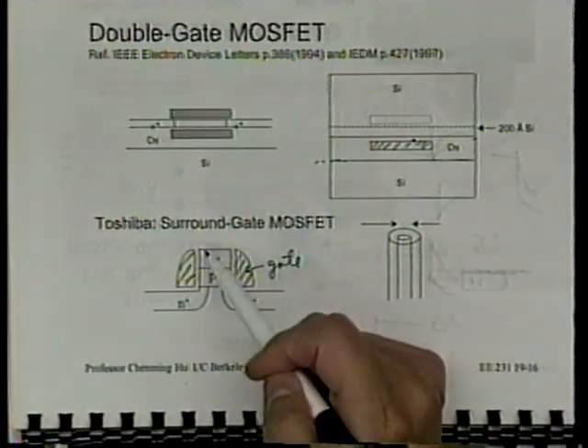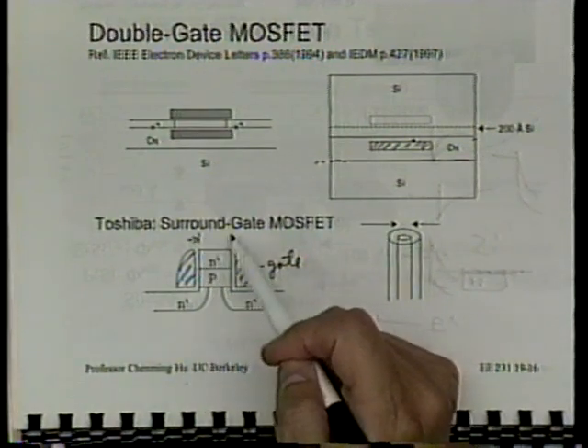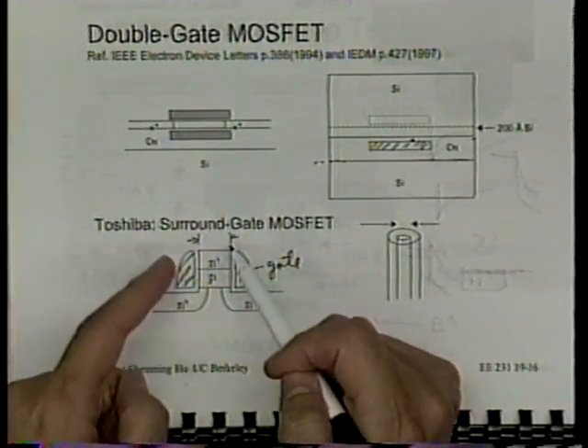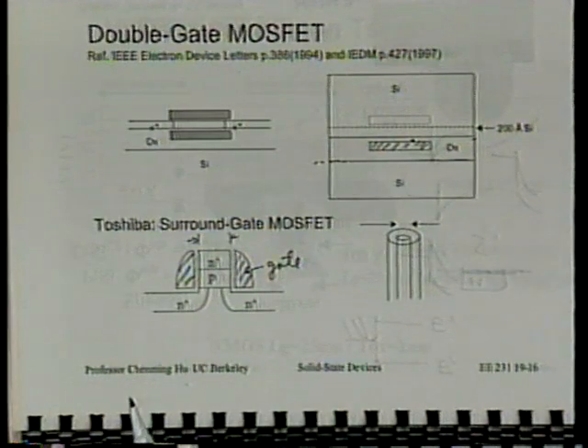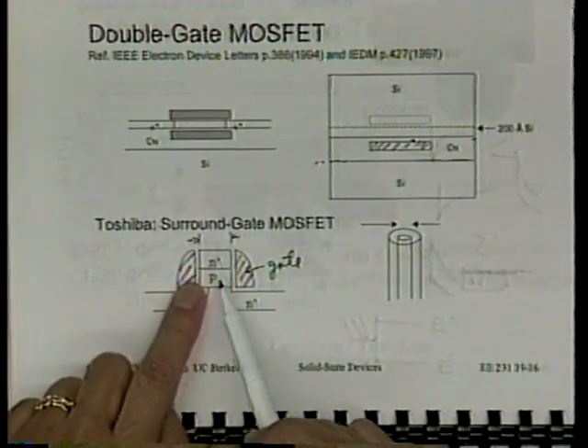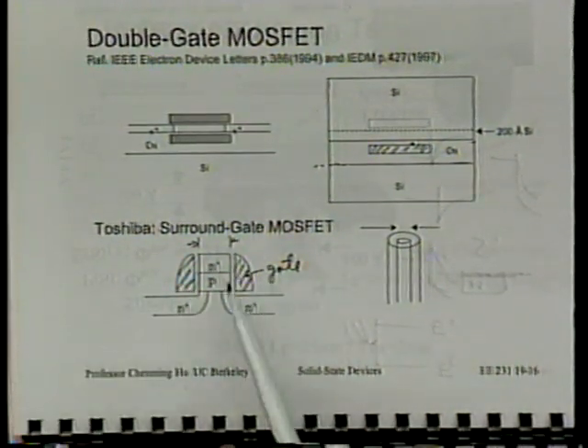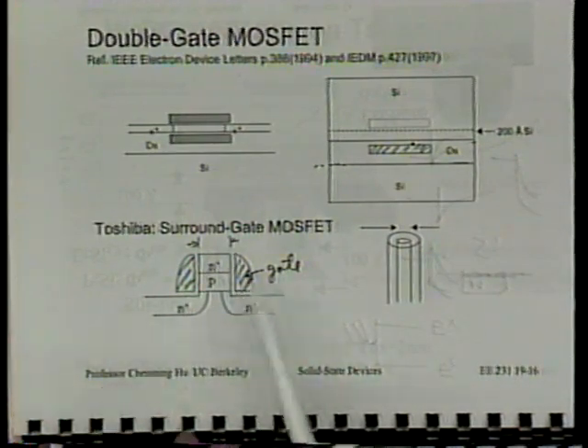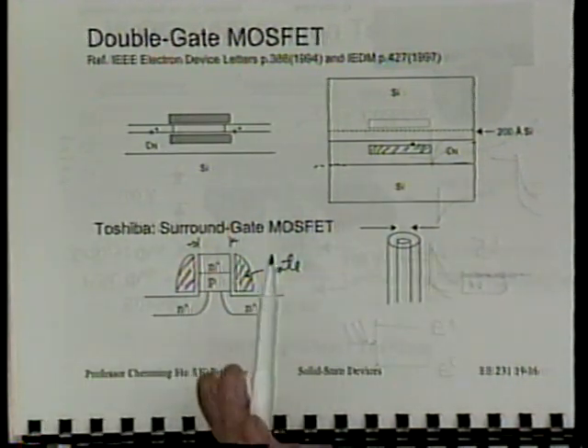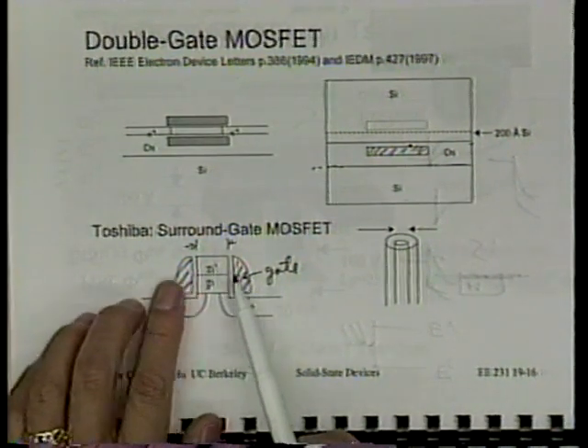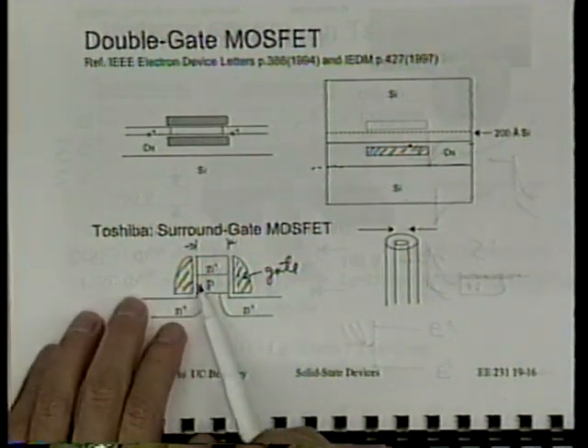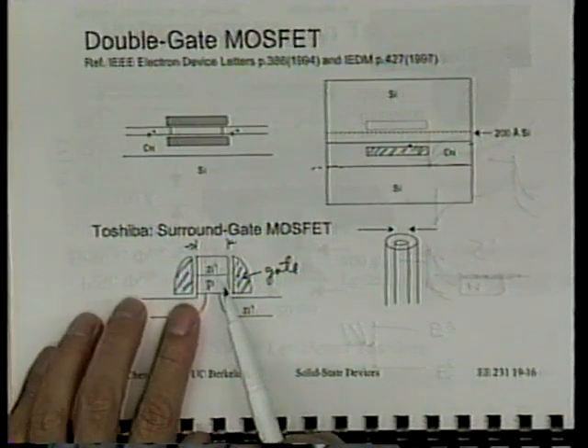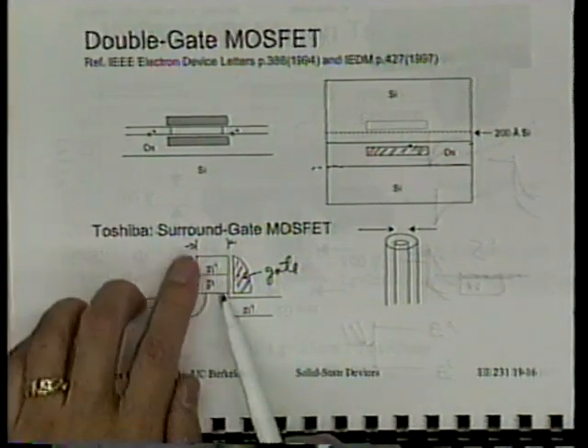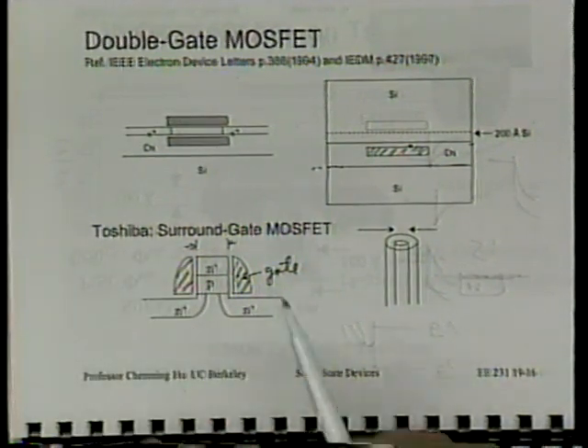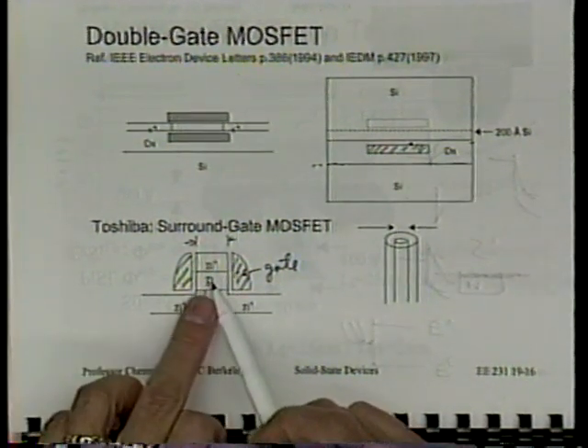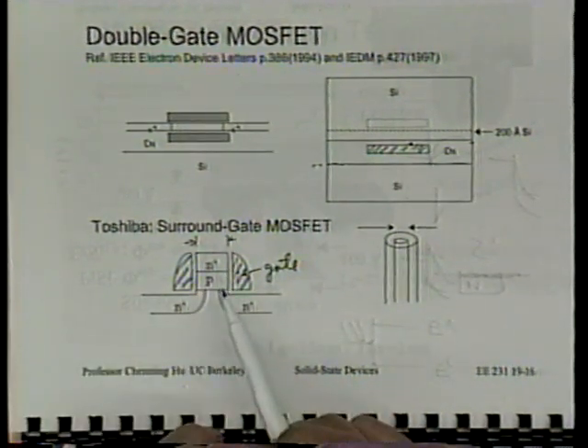Yes? So if you can etch this silicon wall that's thin enough, then you get a kind of double gate I said we want, that it has to be thin, all right? Up until recently, people actually have not been stressing that. They just thought, gee, we're going to get twice the current. This looks nice. But if you want the benefit of really scaling, right, then you have to really make this very thin. Okay? By the way, we think it has to be a fraction of the gate length, channel length, in order to make the gate coupling much stronger than the drain coupling. You see what I mean?